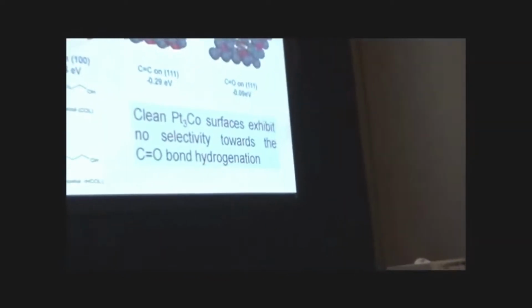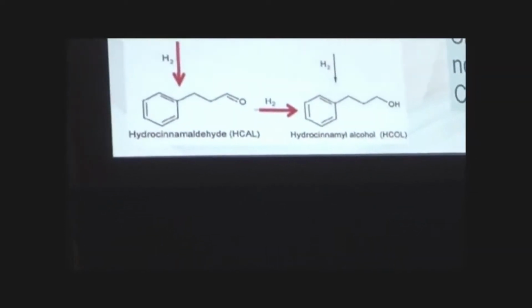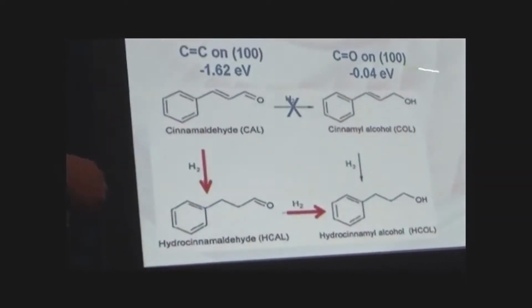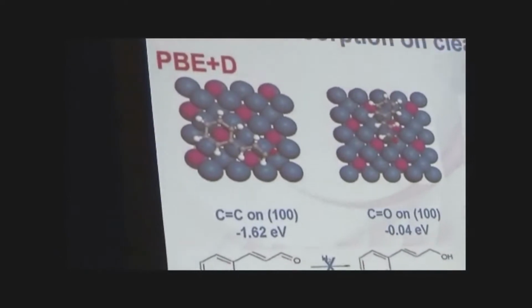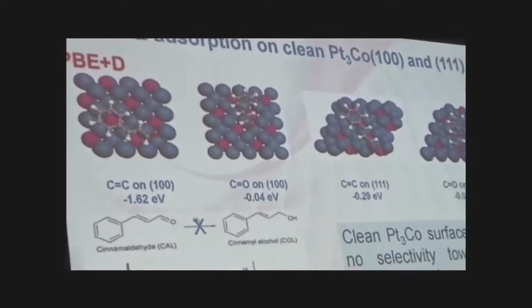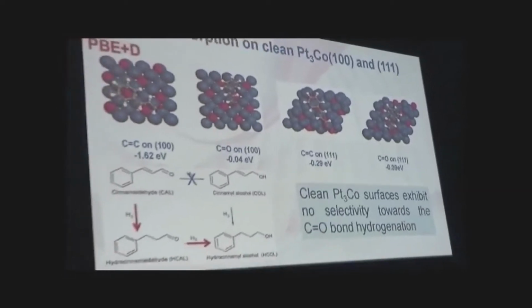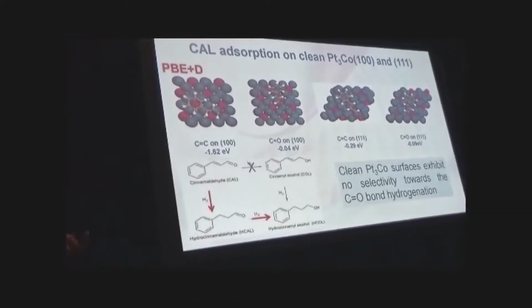To get more insight into this system, we performed DFT calculations. Here, for the clean surface, you can see that C=C bond hydrogenation on the 100 surface and 111 surface is more favorable than C=O bond hydrogenation. So for the clean surface, the main product is the C=C bond hydrogenation product. The reaction goes this way, but not this way. So the clean surface is not a good catalyst for C=O bond hydrogenation.